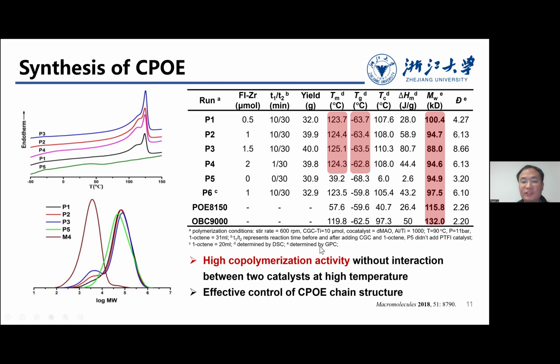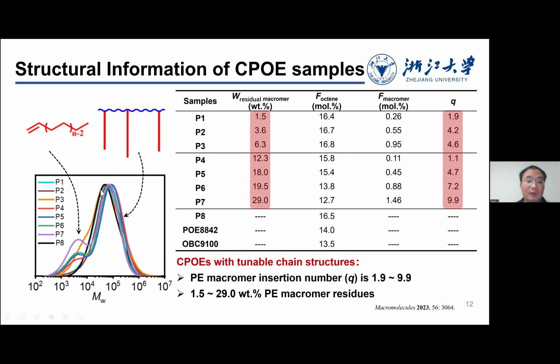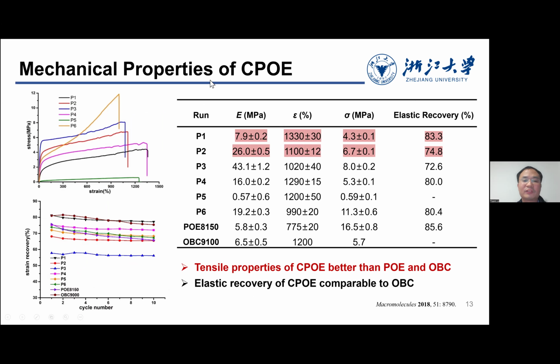So based on this, we can tune the concentration of the two different catalysts, and then we can change the amount of the macromonomer inserted into the backbone. For example, here we still have some residual macromonomer inside, but the number of inserted macromonomers we can tune from 1.9 crystal chains for each chain to 9.9. So in this way, we can tune the chain structure of our comb polyolefin elastomers, and we test the mechanical properties of this kind of CPOE.